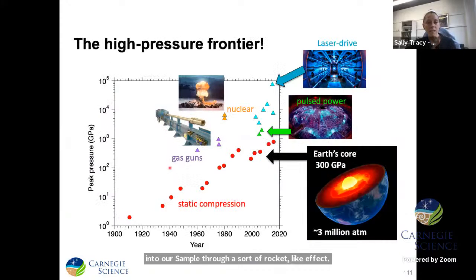And as it turns out, this type of laser drive compression has really started to drive the ultra high pressure frontier since it came onto the scene 15 to 20 years ago. And this figure here illustrates the peak pressures that were achieved using various experimental methods over the last 100 years or so. So from this, we can see that static compression methods, including the diamond anvil cell, have steadily increased in pressure over the last 100 years.